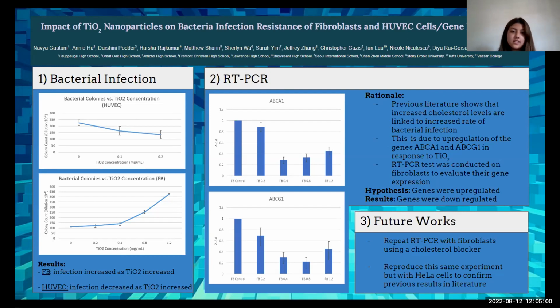So we applied this idea to our experiment and hypothesized that since fibroblasts showed increased bacterial infection with TiO2, the cholesterol secretion genes would be upregulated, similar to the HeLa cells. However, our RT-PCR results showed that the genes were actually downregulated, suggesting that cholesterol is not the mechanism behind the increased bacterial infection. This conclusion leads us into our future work.